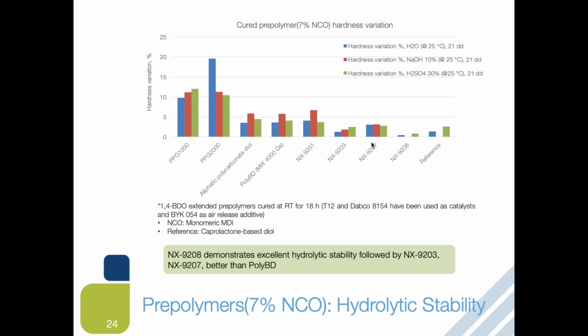The prepared cured prepolymers that I talked about in the previous slide were also exposed to aqueous solutions like water, sodium hydroxide, and sulfuric acid for 21 days. Then we measured the change in hardness. From here, we're trying to understand the hydrolytic stability of those cured prepolymers.